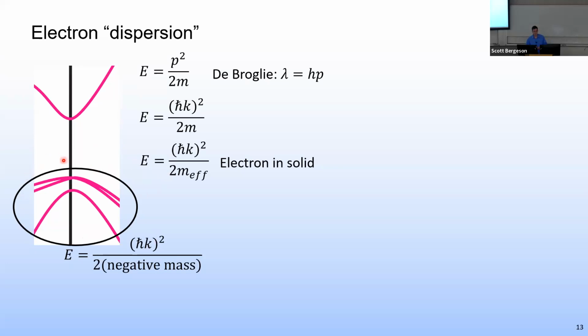But if you look at these bands down here, these are parabolas, but flipped the opposite way. And that means they have negative effective mass, if we want to use the same parabola model. And because we don't like things that have negative mass, we pretend like there are particles that act like sort of anti-electrons, which we call holes. So the hole is the absence of an electron, and the hole has a positive mass, whereas the electron itself in these bands would have negative mass.